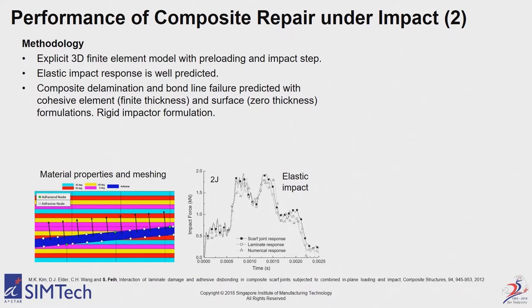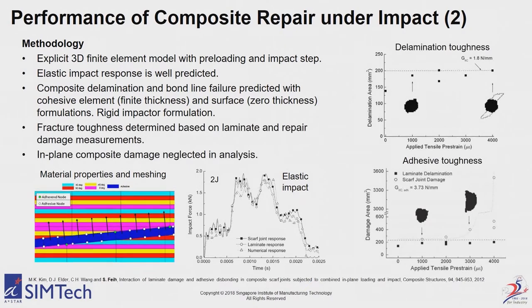We initially did an elastic impact in explicit. We were able to match the elastic response very well. And then we did things we couldn't do experimentally. So we said, okay, what happens if we actually try to match the damage first now? How do we characterize that for the adhesive layers? We could do that. So we could look at the delamination toughness and characterize that under different types of impact conditions. So we had a toughness for the composite. We established a toughness for the adhesive.